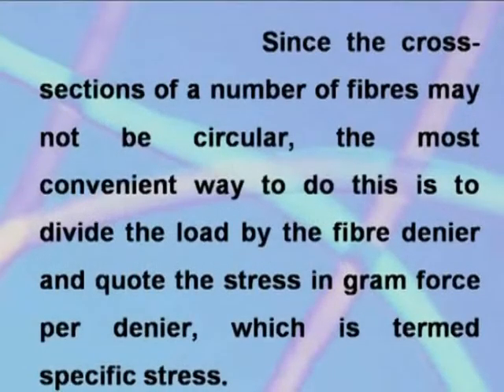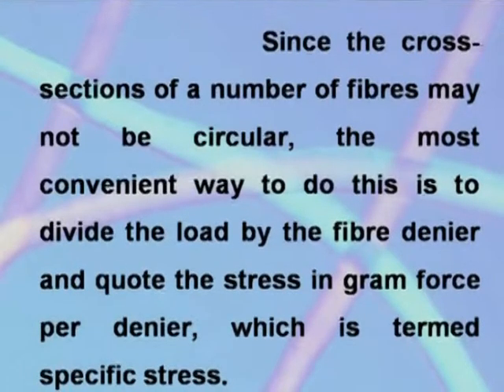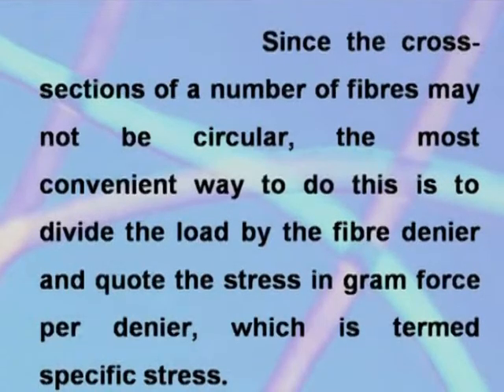Since the cross sections of a number of fibers may not be circular, the most convenient way to do this is to divide the load by the fiber denier and quote the stress in gram force per denier, which is specific stress.